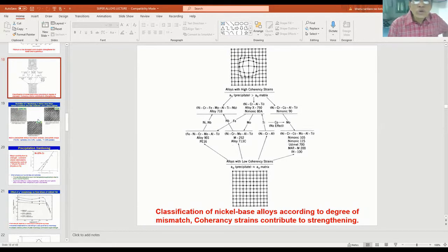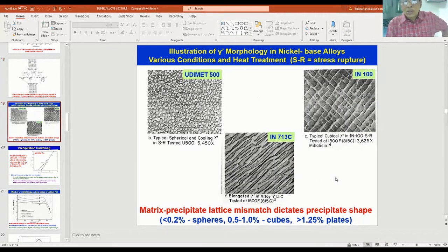Now I am talking to you about gamma prime. First, you see what is the morphology of the gamma prime. That is very, very important. You can see, for example, in alloy Udimet 500, you have spherical shape of gamma prime particles. And in case of IN-100, you have cuboidal shape of gamma prime particles. In 713C alloy, you have elongated gamma prime particles like this.